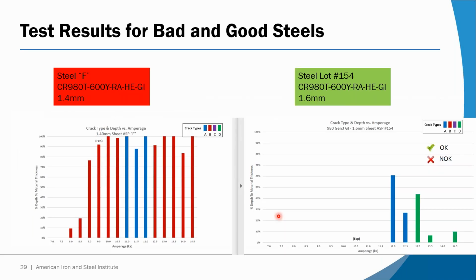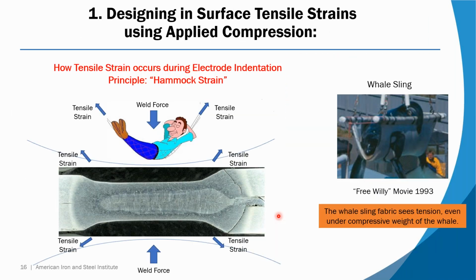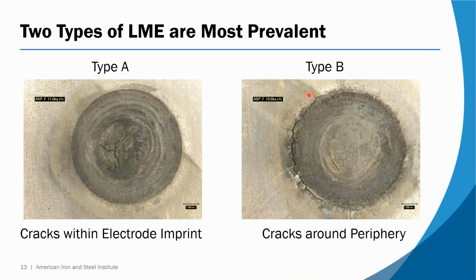That would be the radial crack I showed you—where is it? When you start seeing these spiders going out, I'd call that an extremely low temperature crack, not necessarily the same mechanism as type B. That might be a different thing going on, not associated with indentation but maybe with solidification and cooling. The whole material has hoop strain when it cools, and if that crack suddenly grows a leg and goes sideways, that's really another crack mechanism. So maybe call that type B—I don't know, I'm retiring, so somebody else gets to decide that.